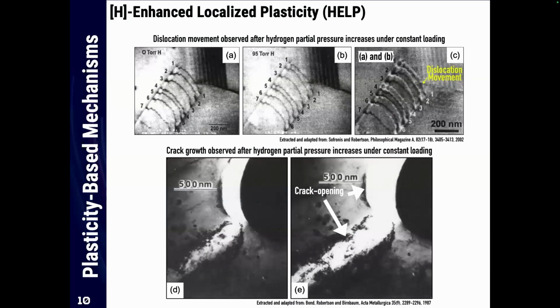The first scientific evidence to support HELP was promoted by Professors Sofronis and Robertson. I forgot if it was Utah or Ohio, I don't remember. They had a tensile specimen holder, and they had a gas cell. They put a hydrogen atmosphere in the TEM with under loading, and they observed that the dislocations move after they release the gas into the TEM column.